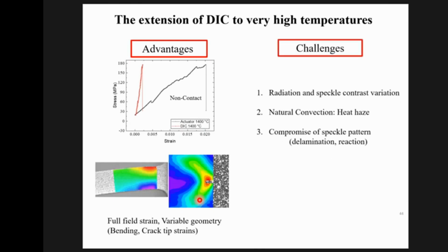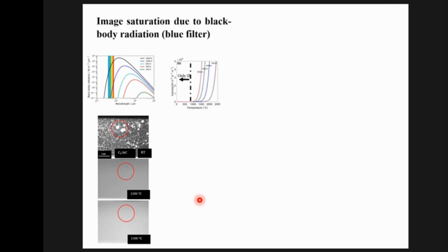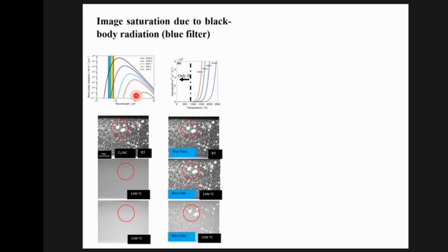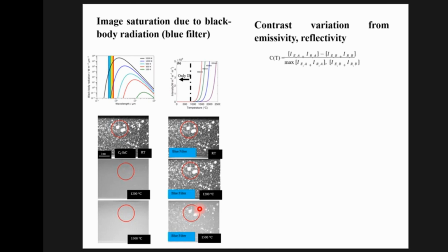So what are the challenges? The first deals with radiation. Second is heat haze, and the third is chemical reaction. Let me just show you some examples of these. So here is an image. This is a carbon fiber silicon carbide composite at room temperature, 1200 and 1500. 1500 is invisible because the black body radiation completely swamps your detector. These curves show you the variation of the black body spectrum with temperature. But if you introduce a filter, you can see now that you can go up to 1500 degrees and still have enough contrast to make measurements. So that's what most of that instrumentation was, both the illumination as well as the filters and the detection side.